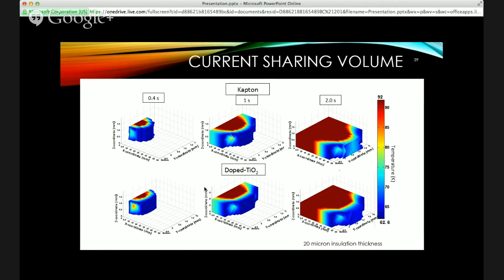And if you did that, what you would see, if I looked at these two now, comparing doped titania and Kapton at 2 seconds, it's not a big difference, but you can see the shape difference. But if you look at the temperature above 92K, what you would see is the doped titania would have a lower temperature than the Kapton in that section. And that's important to know when thinking about construction.